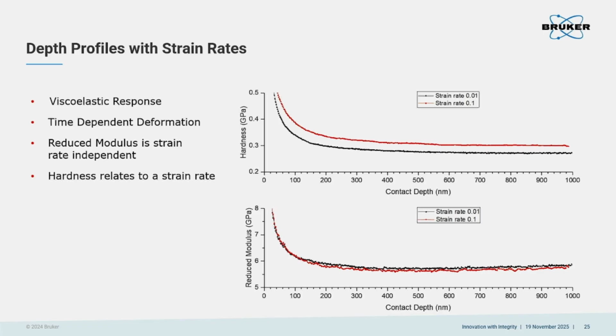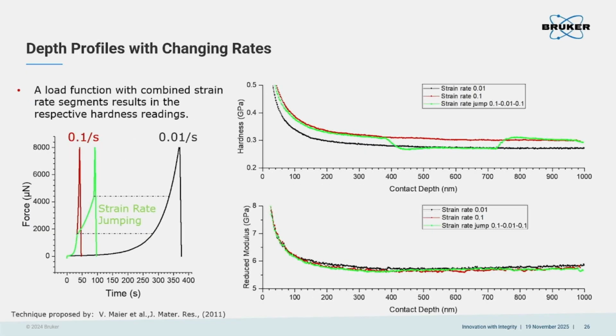And in order to check this strain rate sensitivity, we can design a very special experiment to check the hardness sensitivity to strain rate, which is this. We can design a very special loading function, as shown by the green dots here. So we can change the strain rate. We use a higher strain rate at the beginning, and then in the middle, we decrease the strain rate to a lower one for a period. After that, at the very end, we increase the strain rate to the higher value again.